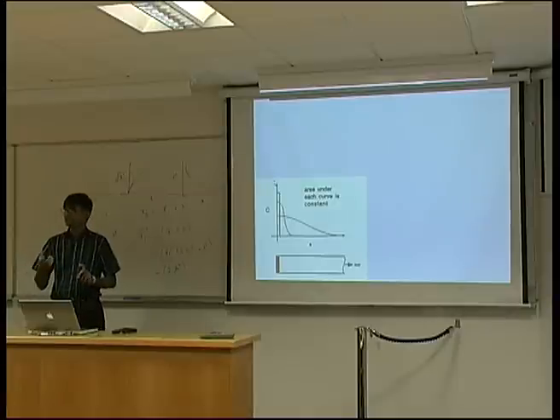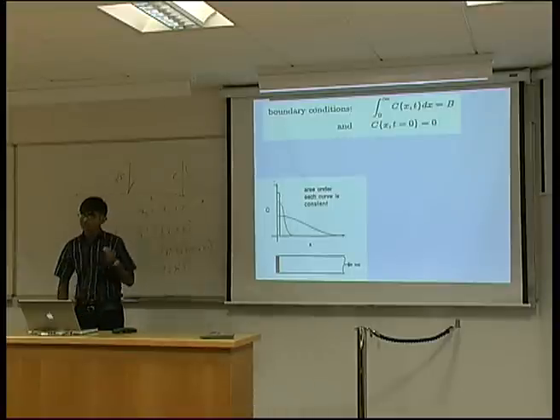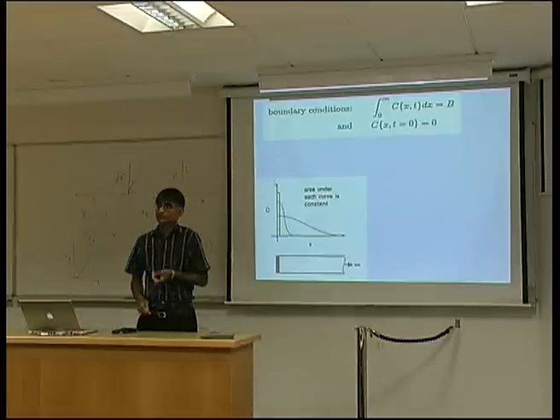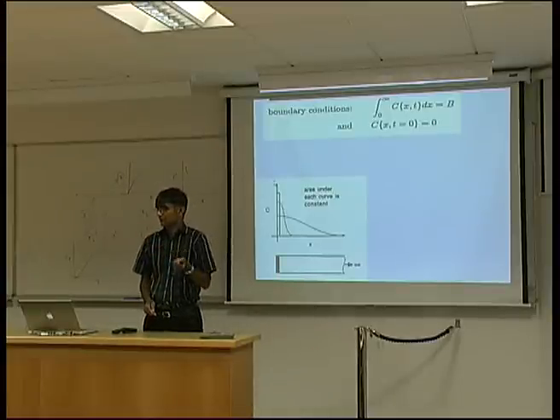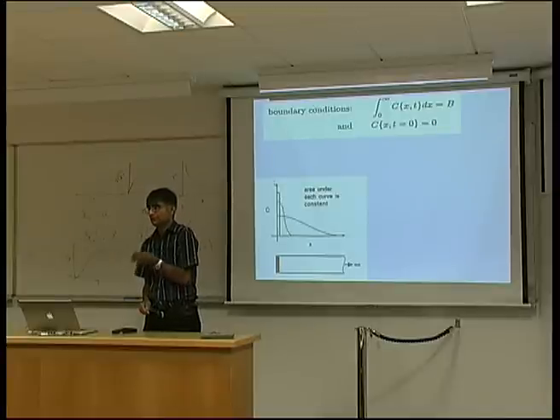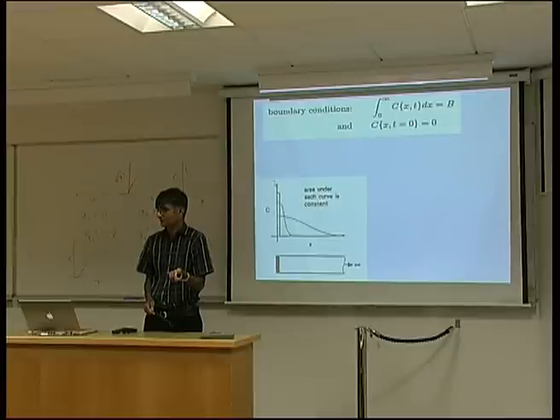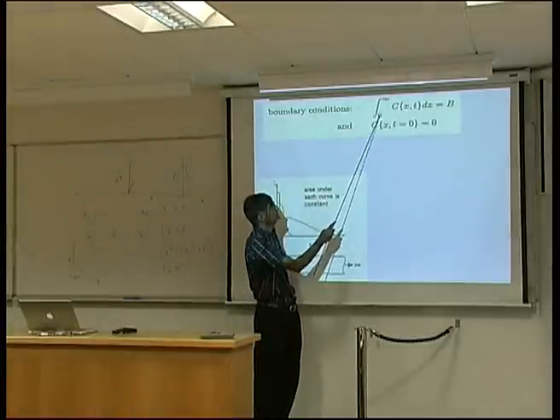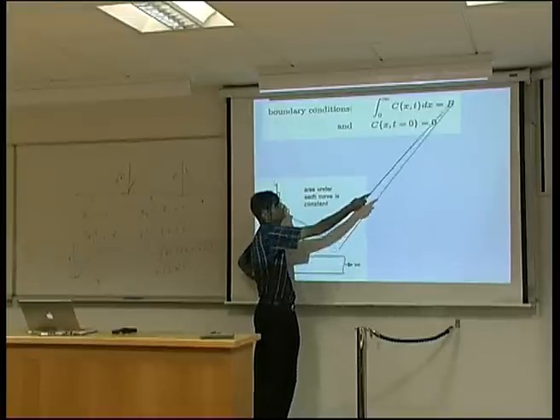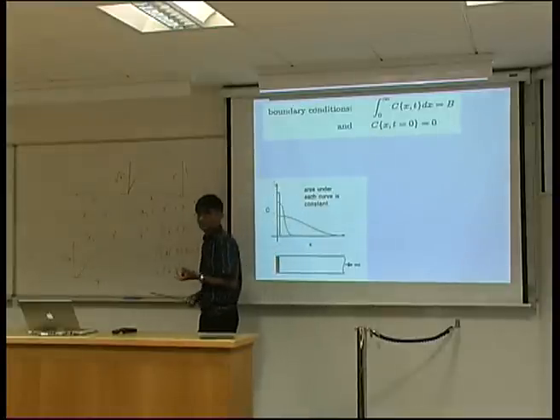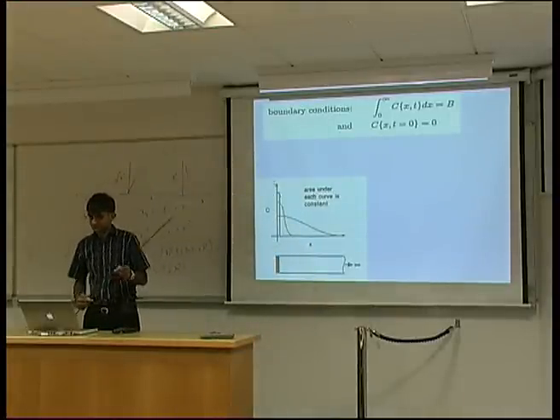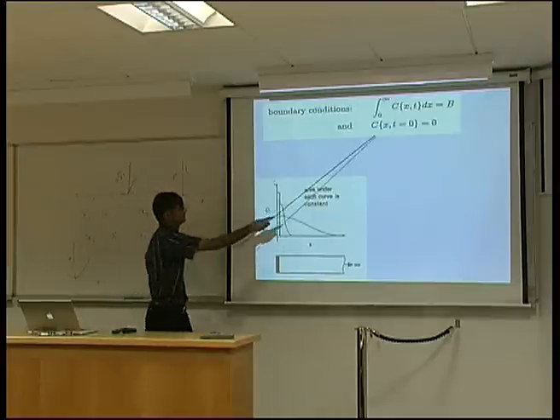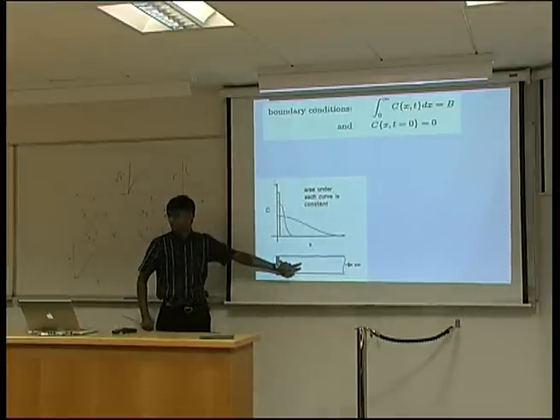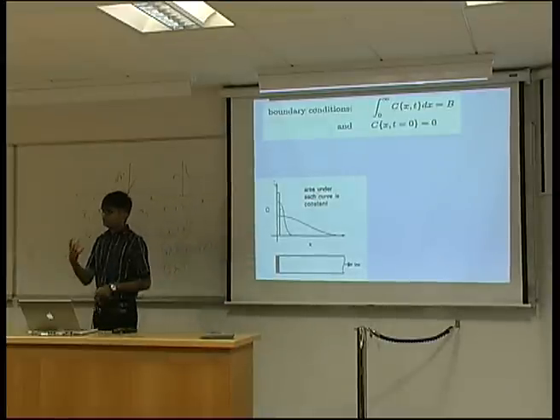Now, obviously, you have to use Fick's second law to treat this, and subject to some boundary conditions. And the boundary conditions, the first one is that we are not putting in any more mass. We just put a thin layer of phosphorus on the surface and we are allowing it to diffuse. So at any instant of time, if you add up all the phosphorus, it's got to be the same amount that you started off with, right? Conservation of mass. That's this condition, that the integral of all the solute, function of distance and time, must be the value you started off with. Straightforward. And the second thing is that when we start the process, there is actually no solute present in this bar. So that's what we call boundary conditions.